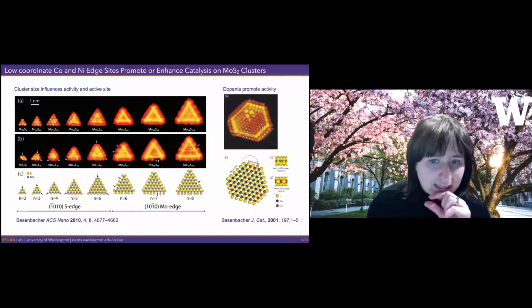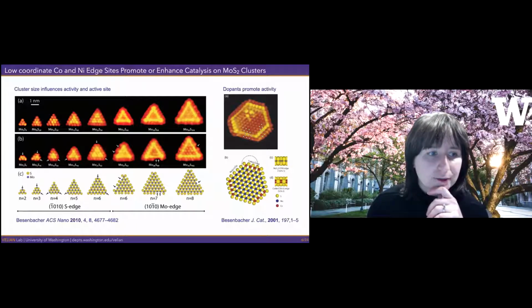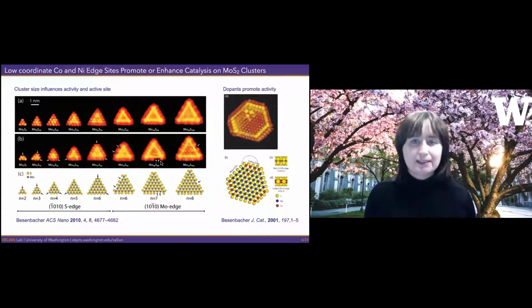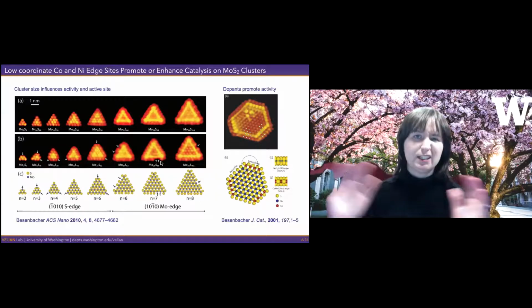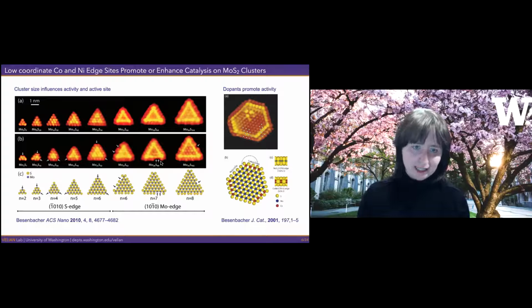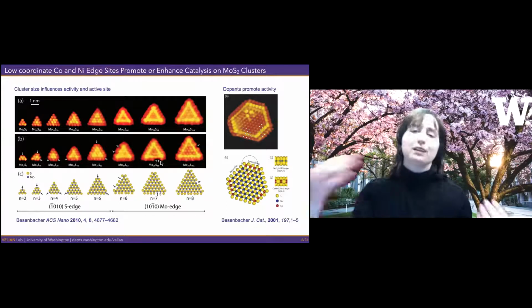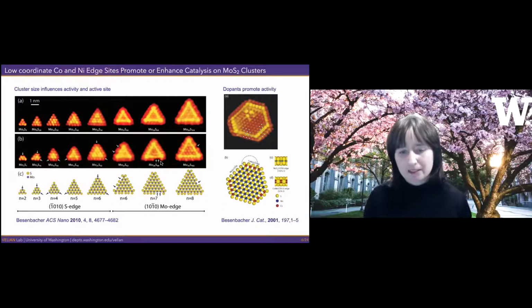But as we look at what happens during the reaction, we see that the active sites, which are indicated by these arrows, are positioned in different places on the flake. And so in the small sizes, they're at the corners of the triangles, whereas as we look at the larger ones, they're on the sides. And that's one of the reasons why the selectivity is different as you go to different size flakes. Because the sterics are different, the electronic properties of those sites are going to be different.